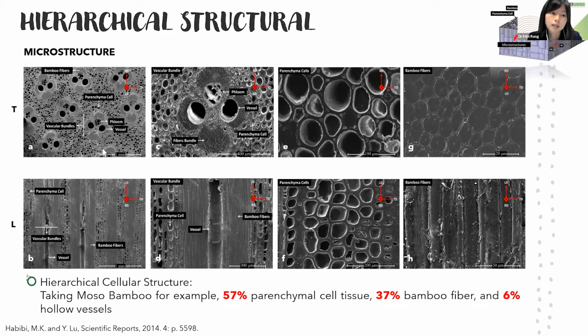Here the scale bar is around 1 millimeter, which we can see by our eyes in this area. And here it's around 400 microns, until here it is 20 microns. From the larger image to the smaller image, we can see that it contains different microstructures inside. We take this one as an example. The bamboo contains some vessels here. The vessels transport the water and nutrients, and they are all surrounded by fibers.